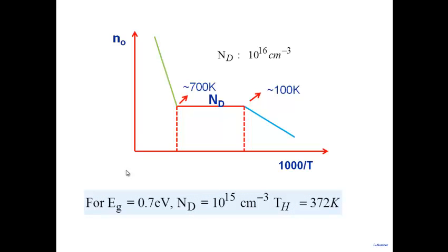But then I give you another example. Suppose I take a semiconductor 0.7 eV, and I put 10 to the power 15, this temperature goes to 100 degrees Celsius. Now this is only for 0.7. Now suppose I have 0.35. Where will this temperature go? So you're seeing now, I've put 10 to the power 15 doping, but my semiconductor is behaving as intrinsic, right? So that's one problem that you see here, okay? So the temperature begins to affect your device a lot because the energy gap is so small, so thermally generated carriers are so large, okay? So that begins to bother you.